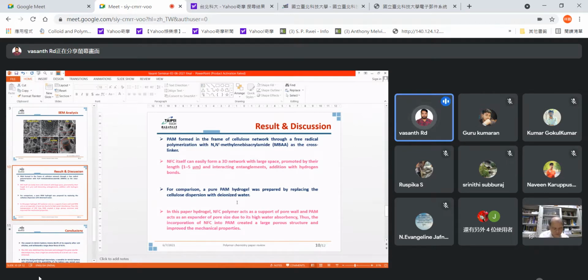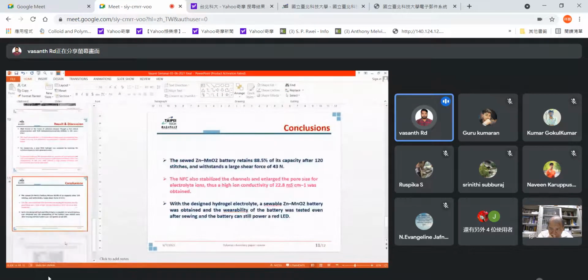So for a comparison, a pure PAM hydrogel was prepared by replacing the cellulose dispersion with deionized water, as I mentioned before. In this paper, the hydrogel NFC polymer acts as a support of pore wall and acts as an expander for pore size due to its high water absorbency, as we see from the SEM images. Thus, the incorporation of NFC into PAM created a large porous structure and improved mechanical properties.